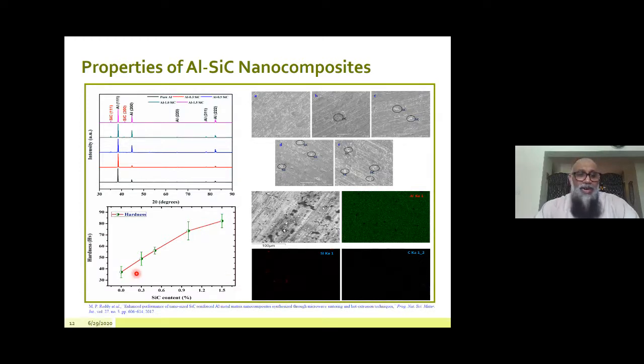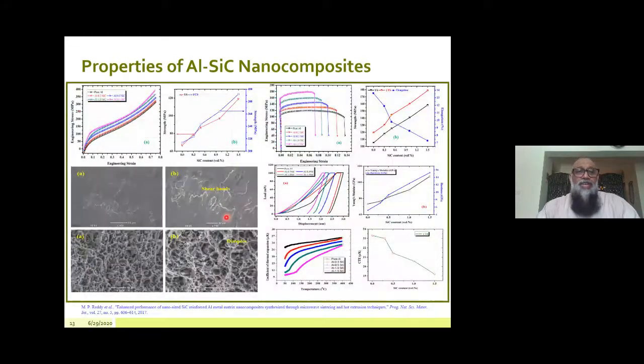So this is the hardness versus silicon carbide content graph. We can see that the hardness of the aluminum matrix increases with the increasing amount of silicon carbide as a reinforcement. I will explain why it increases with increasing amount of silicon carbide. So here are the compression testing results of the developed nanocomposites. We can see that yield strength and ultimate compressive strength increase with the increasing amount of silicon carbide content in the aluminum matrix.